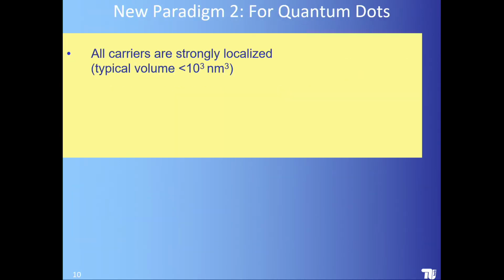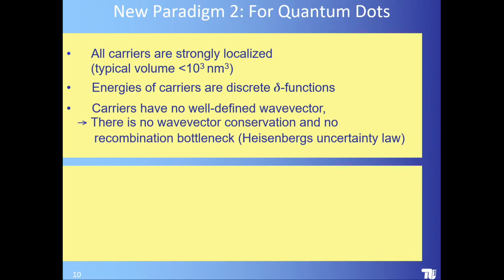In nanostructures, everything has to be reversed. First, all carriers are strongly localized in a volume which is approximately 10 to the third cubic nanometer. The energies of carriers are discrete delta functions. Yeah? So there is no energy dependence on momentum vector. The carriers have no well-defined wave vector. There is no wave vector conservation and no recombination bottleneck. That is a function of this here. This is very simply what everyone has learned at the beginning of his studies, Heisenberg's uncertainty relation. If something is strongly localized in R space, it's completely delocalized in K space. Yeah? So these are fundamentals of quantum physics, 1926.